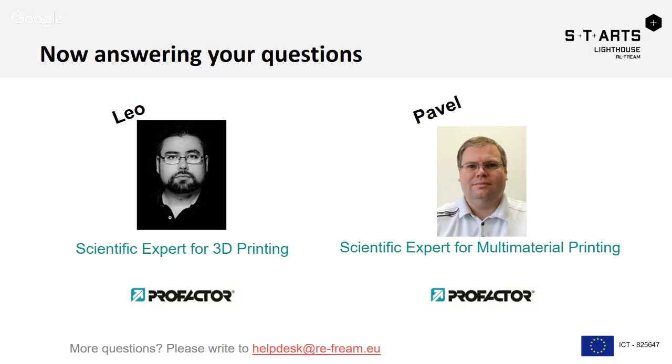When we have, just as an example, a wooden piece, we try to print the conductive material on it and try to sinter it. That's also one key aspect in enabling a conductive path, and we see how it behaves, whether the natural material can withstand the sintering conditions, or also the compatibility of the material itself. Just a little bit of insight, not going much into detail. I hope this answers the question to your satisfaction.